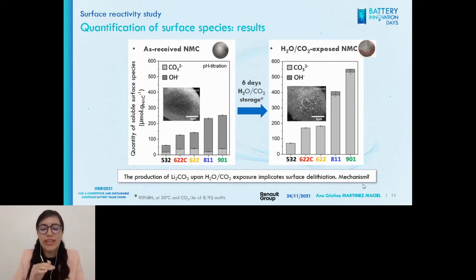You can see that the amount of carbonates is increasing with the nickel content. For the 901 material, it has a lot of carbonates produced on the surface, which implies that there is a delithiation occurring. But in the literature, it was not clear how.